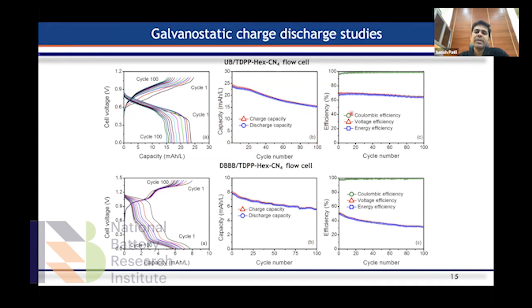So, our Coulombic efficiency was not degraded as compared to the capacity when you compare with the cycle number. And then this is the charge discharge capacity for a different material, where here we take UB-TDPP hexyl CN4, which we developed in our lab, and built a cycle. So what we see here is, when we characterize this battery at room temperature, as a function of time or discharge density, indeed the capacity fades lower and lower. But we could go up to 100 cycles.